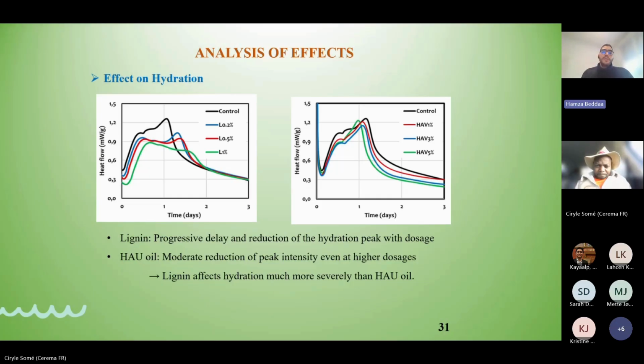For the hydration, using small or limited rates of lignin and waste vegetable oil, we can see that with the lignin there is a delay in the hydration process. And this delay is due to a chemical reaction between lignin and the calcium that we can find in the phases of clinker.